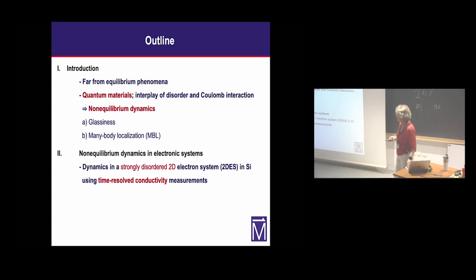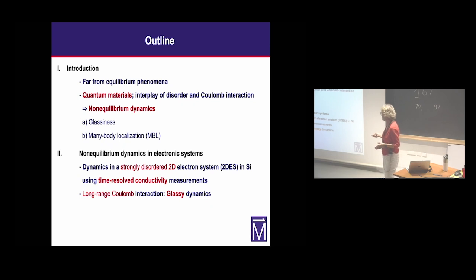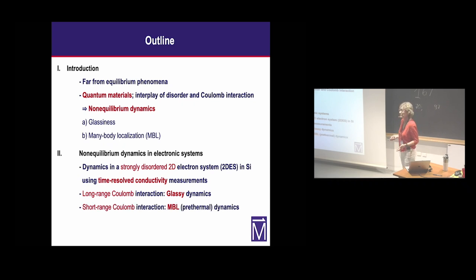So what we have found is that in the case of a long-range Coulomb interaction, the strongly disordered 2D electron system exhibits glassy dynamics, whereas in the case of a short-range Coulomb interaction, the dynamics is completely different, and in fact, it is consistent with many-body localization. And at the end, I will discuss some possible directions for future research.